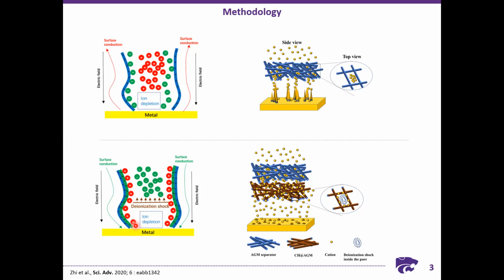Because of this surface conduction, even when there is a concentration gradient where there are no more metal ions present in the vicinity of the surface, we can see a current which is higher than the limiting current that is limited by diffusion. So it is called the over-limiting current, because of this surface conduction phenomenon.